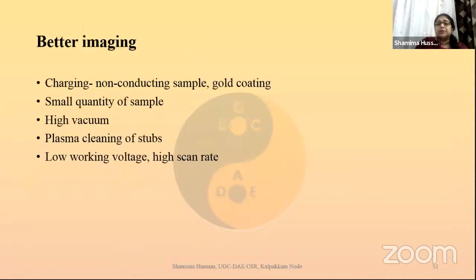For better imaging, we need to have this gold coating. We usually use a very small quantity of sample which is required. We need to have very high vacuum. So the sample must be vacuum compatible. Especially for biological samples, we need to ensure that they are dry. Otherwise, they start releasing water molecules, which are very dangerous for the instrument. We will never get the image, we will spoil the system. So usually we talk of cryo drying and we dry the samples for that.